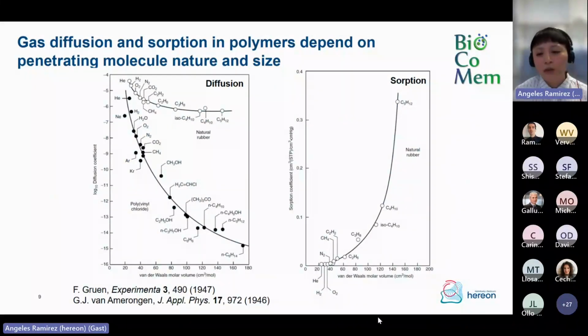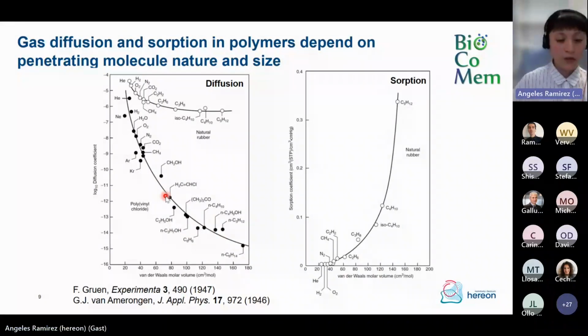Now we come to the choice of which polymer to use. And so for gas separations, we normally use amorphous polymers, which can be above or below their glass transition. Now, in the case of glassy polymers, we see that the diffusivity will depend strongly, as I mentioned before, on the kinetic diameter of the gas molecule. We see here a strong dependence. So the smaller the gas molecule, the faster it will diffuse through the polymer.